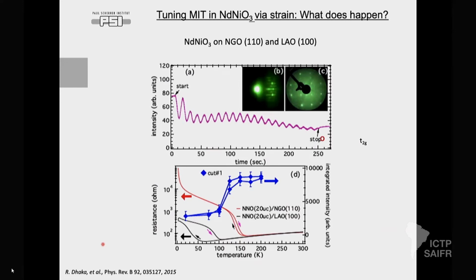Okay, so this was on the lanthanum nickelates. We work on the NdNiO3 nickelate, where we already showed the metal-insulator transition, and we also wanted to understand what happens if the film is grown on two different substrates: on NGO, which gives tensile strain, and on LAO, which gives compressive strain. For this, we use our tool, which I showed you before, the pulsed laser deposition system, directly attached to the ARPES station at the beamline.